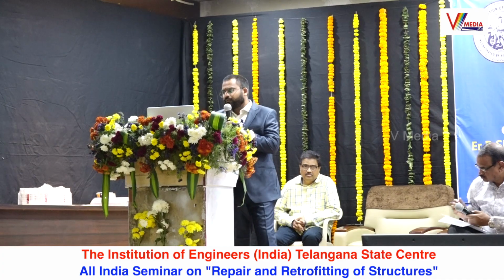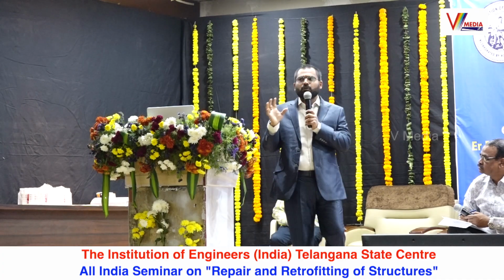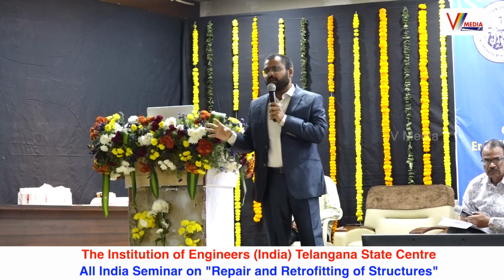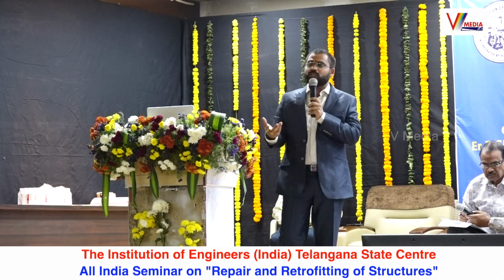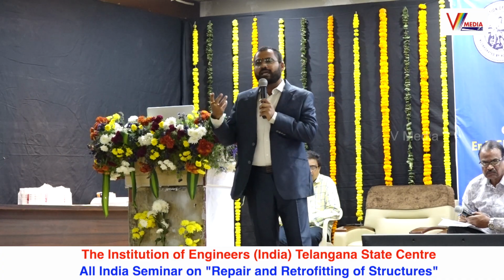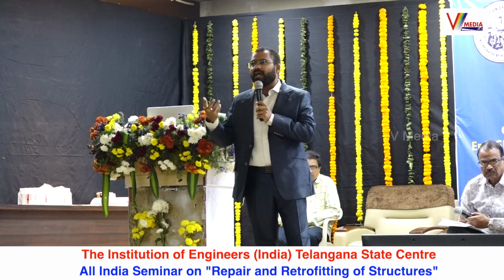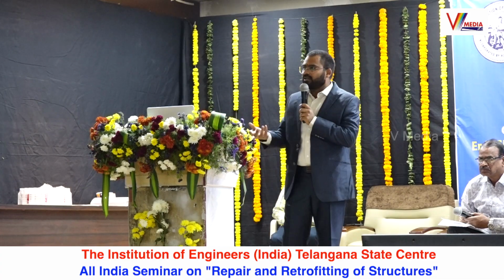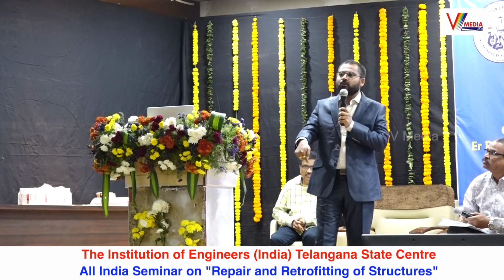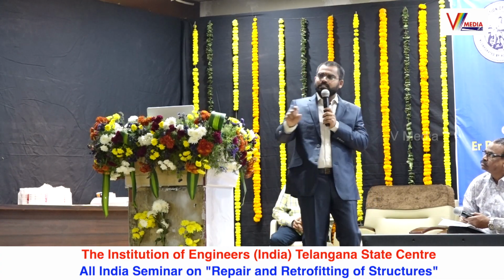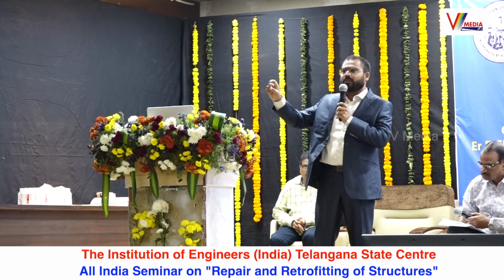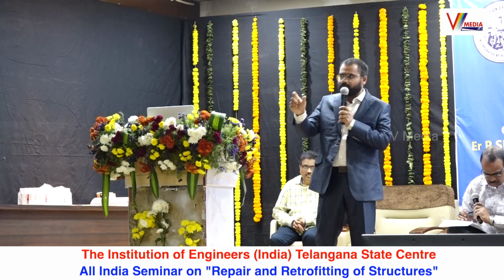Now, one more thing: we see many rebound hammers available in the industry. But how do you ensure whether we are using the proper rebound hammer or not? You need to calibrate the rebound hammer on an anvil. There is a material called an anvil. You strike the rebound hammer on it, and the number displayed on the anvil should be displayed on the instrument. Then only the rebound hammer is said to be calibrated.